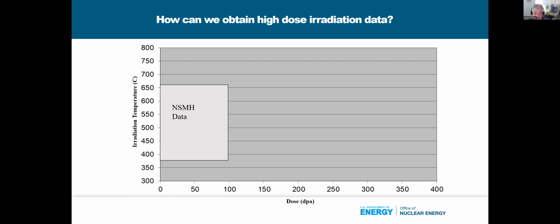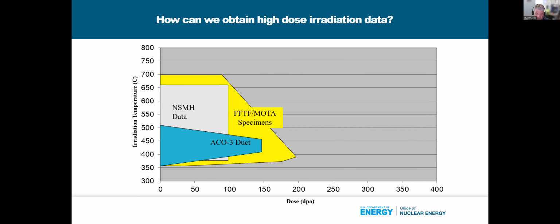And there is, from the Nuclear Systems Materials Handbook, data out to 100 dpa on mostly austenitic stainless steels, maybe a little bit on ferritic martensitic, but mostly austenitic stainless steels. From an analysis done about 10 years ago, which I just summarized in this talk, on the ACO-3 duct, we got some data out to about 155 dpa, but over a specific temperature range. From materials that were irradiated in FFTF, there were actually some that went out to even 200 dpa. So there is a lot of irradiation data available.